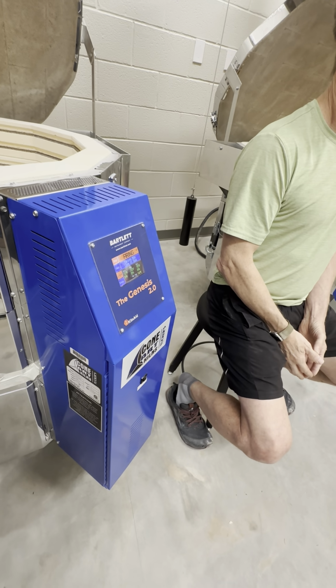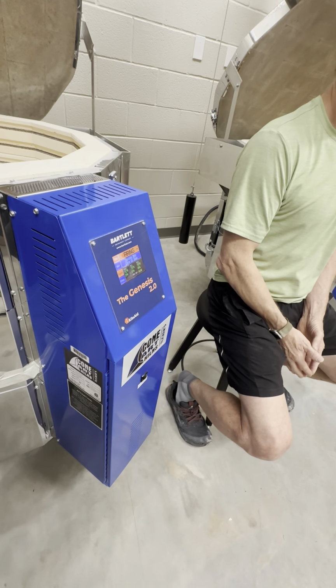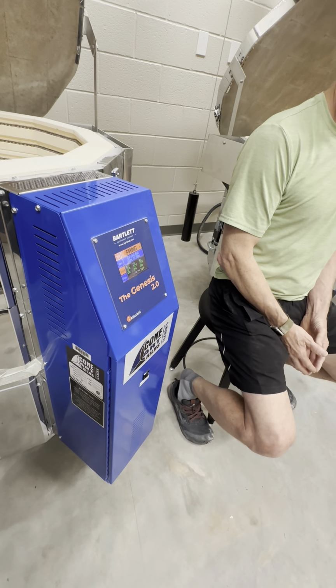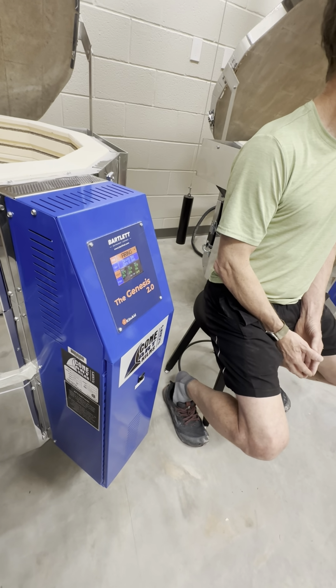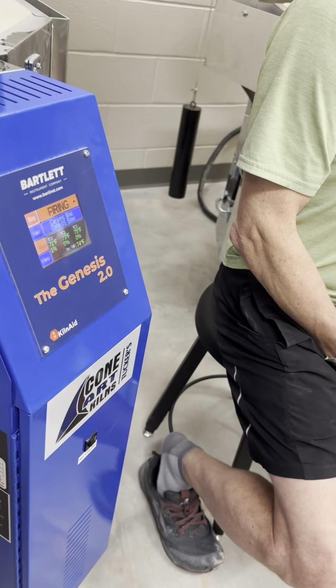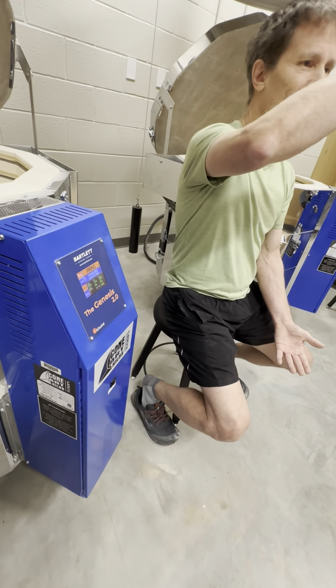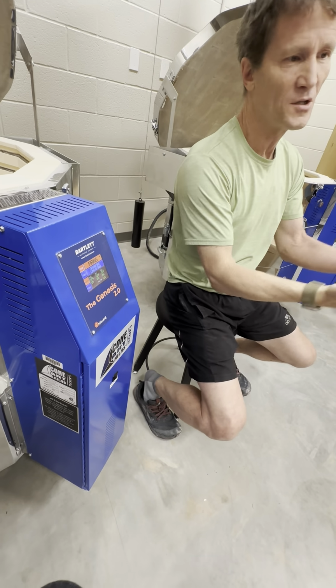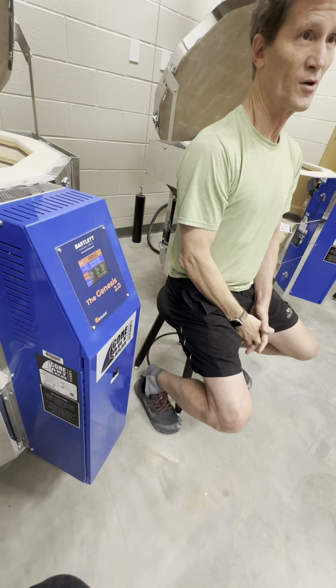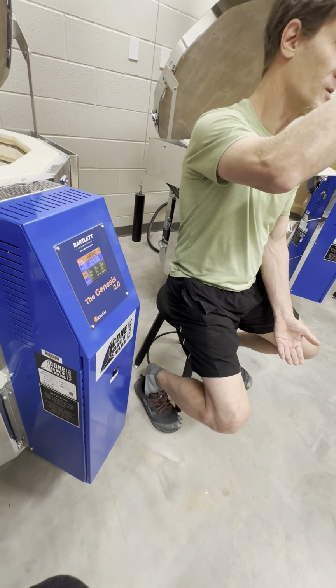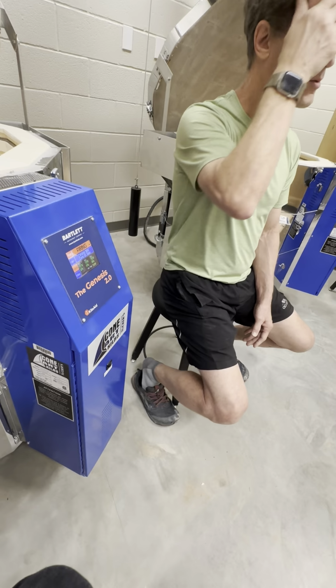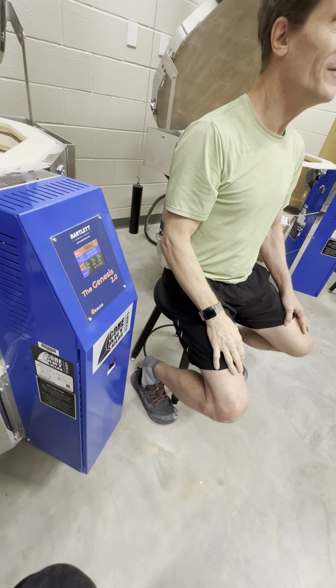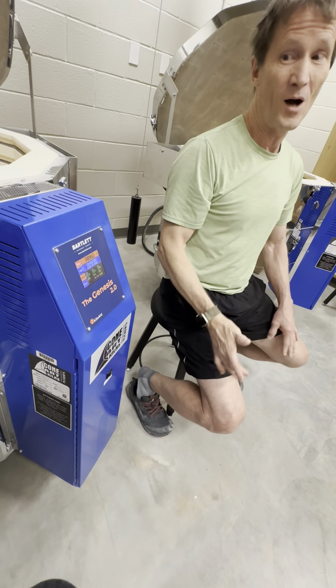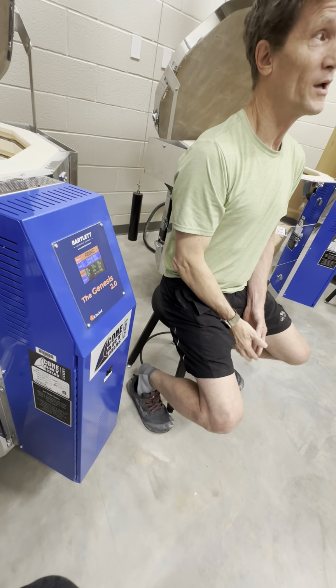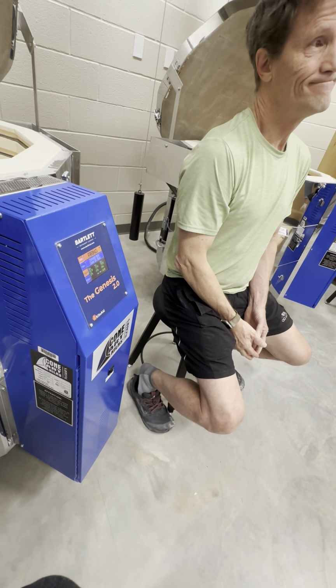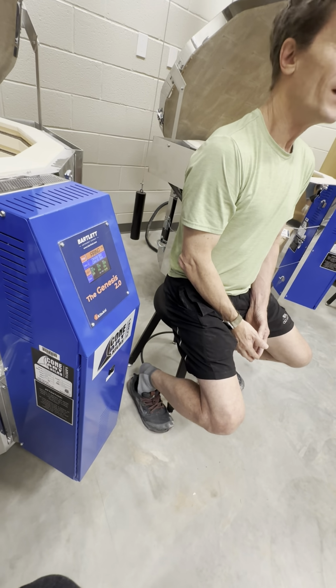Do you always recommend 3 hours on slow? No. It depends on what I'm firing. Sorry to be glib, it depends on what I'm firing. If my students are getting ready to start this, it's a 24-inch classic vessel that they're putting a contemporary surface on. These pieces are all going to be this big. In my big oval, I'll be able to put 6 or 7 in there. Even though they're going to be put in the kiln dry, I'll probably preheat those because they're so big, for 7, 8 hours.